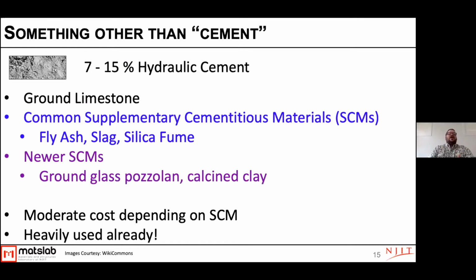We can use what are called supplementary cementitious materials. So these are things like we grind up limestone and mix that in with the cement. We use waste byproducts from other industries like fly ash and silica fume. And then we have newer products coming on, like ground glass pozzolan, which is crushed up waste glass, and calcined clay, which is clay that has been heated up. Locally, we have a new plant for ground glass pozzolan that came online in Connecticut that is really going to help us access that great new SCM.